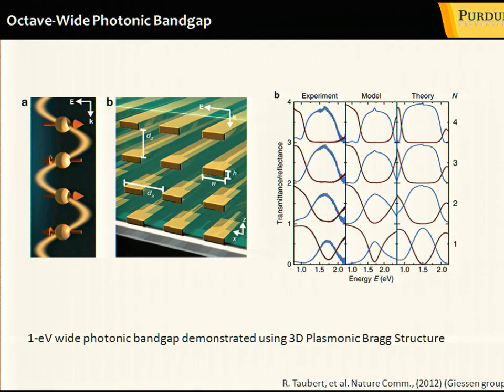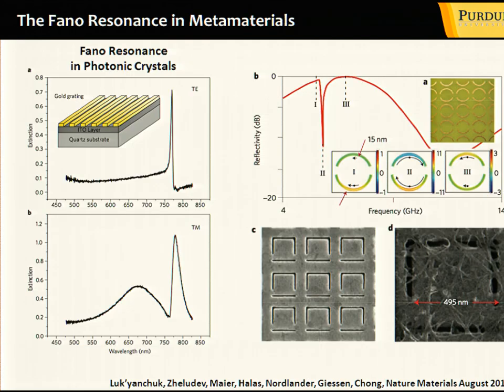So this is an example of a Bragg stack of plasmonic structures, which could be arranged in such a way that when light propagates in the forward direction, the interference is fully destructive, so that light actually cannot go through your metamaterial. And when it propagates in the backward direction, the interference is constructive, so that light is fully reflected. You could create a band gap, a stop gap extremely large, with a width close to one eV, and you could see here that in this range you have almost all light reflected with no transmittance.